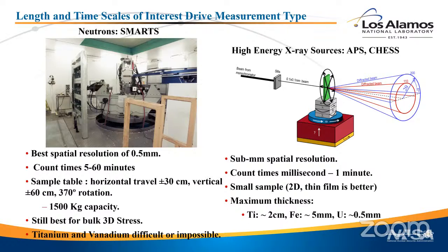The problem is you get much less grain statistics. So if you're trying to relate it to macroscopic plasticity, that's often hard if you're only seeing 1 or 2 grains, because grains can be outliers. For the rest of my talk, I will talk about X-ray and neutron. It doesn't really matter which one I'm talking about. How you interpret the data in terms of microstructure is very similar. How you choose your probe depends on the problem you're doing. If you're doing something slow and a big component, then you use neutrons. If you're doing something fast and a small component, then you use X-rays. There's a little bit more that goes into it, but that's 90% of that decision tree.